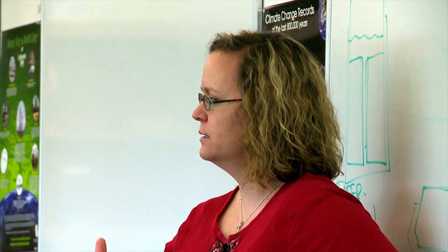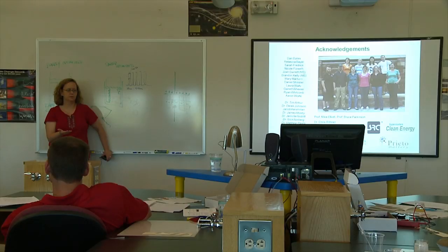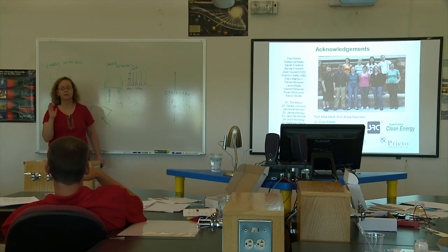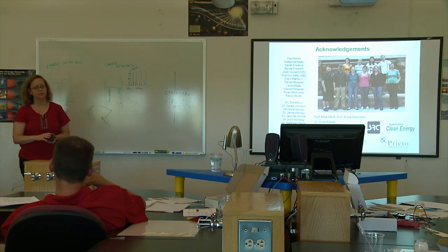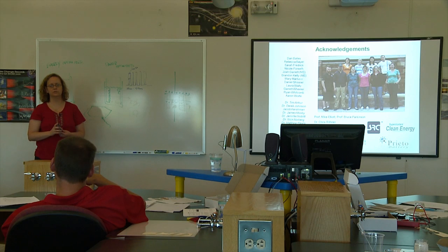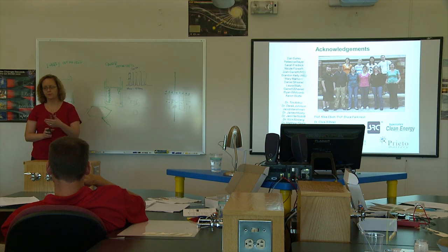And then it's exactly the same idea as making cupcakes versus making a sheet cake. You basically put metal on the bottom, and then when you plate this copper antimonide, it grows from the bottom up through this hole. Then you can selectively dissolve away the aluminum oxide, and you're left with these tiny little nanowires. And they are really fast. They are way faster than the copper foam that I showed you. The trick, though, is that it does take these two steps, the anodizing the aluminum and then plating, and then you do have to dissolve the aluminum oxide away.